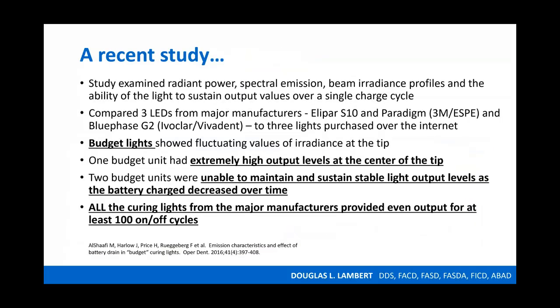This is interesting, a recent study that examined the radiant power, spectral emission, and beam irradiance profiles and the ability of the light to sustain output values over a single charge cycle. It compared 3 LED lights from major manufacturers to 3 that they were able to purchase over the internet. And what they found with these budget lights, they showed fluctuating values of irradiance at the tip, extremely high outputs at the center of the tip, unable to maintain and sustain stable light energy outputs as the battery decreased its charge over time. And yet all the lights from the major manufacturers provided even output for at least 100 on-off cycles. So again, the idea of buying from a reputable source may be the key here when you talk about purchasing a curing light.